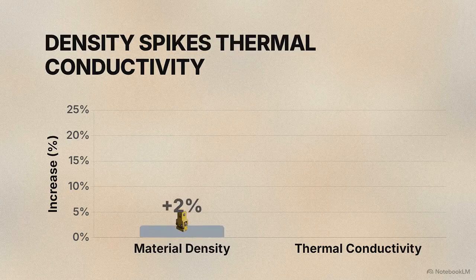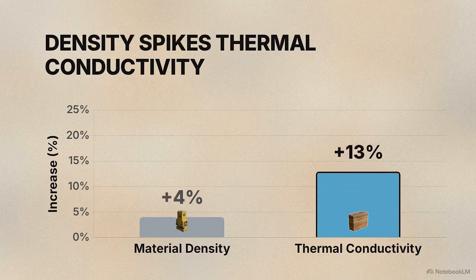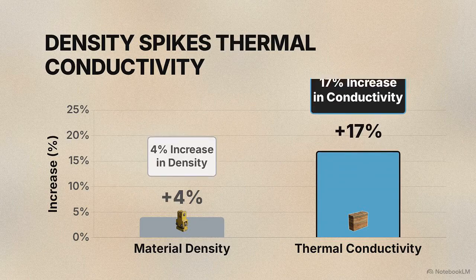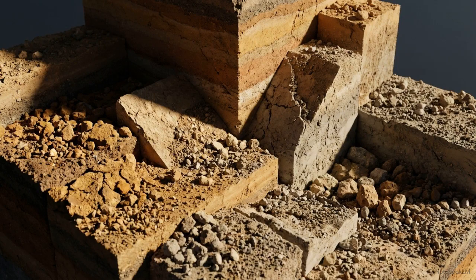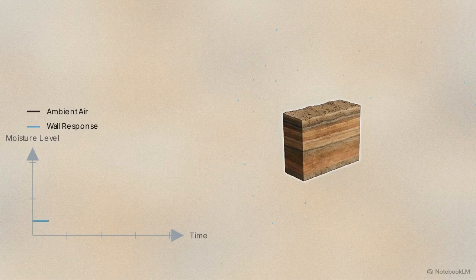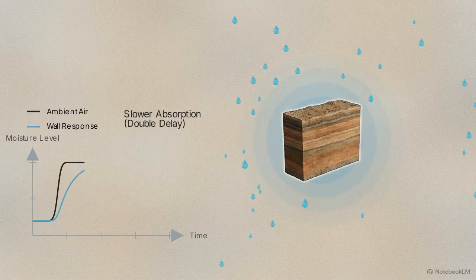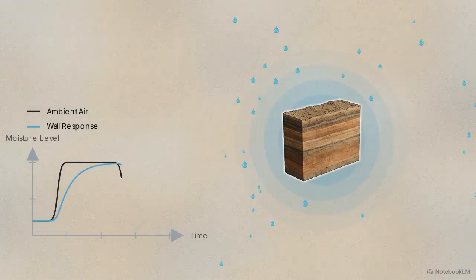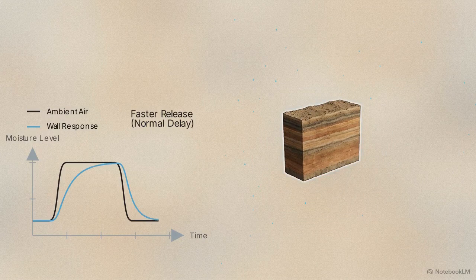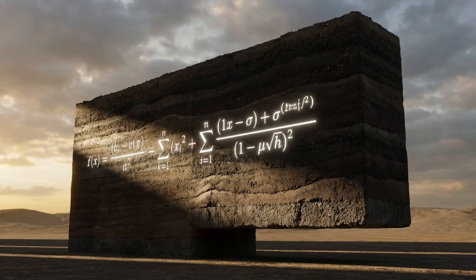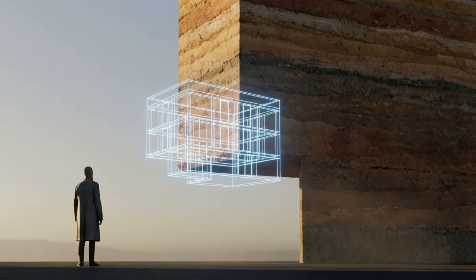They found that a mere 4% difference in the density of the packed earth altered its thermal conductivity by 17%. They also observed that while grain size barely affects moisture absorption, high ambient humidity nearly doubles the material's hysteresis, which is the delay in how the wall absorbs and releases water compared to the surrounding air. Because they mapped these behaviors linearly across different compositions, the researchers developed approximation coefficients. Engineers can now model accurate thermal conductivity without paying for site-specific soil lab testing on every project.